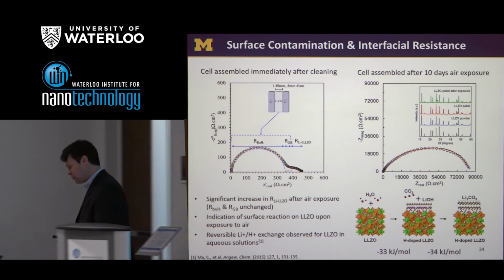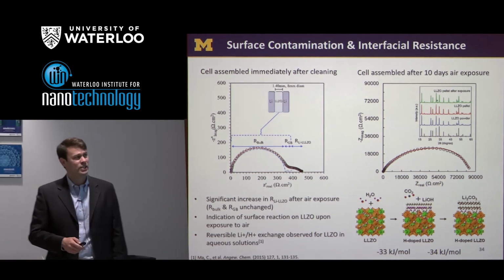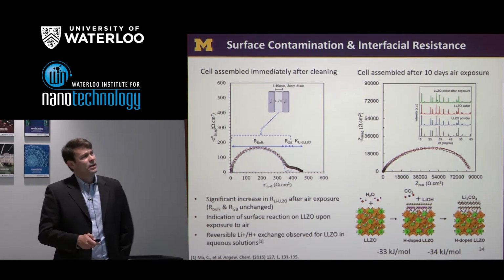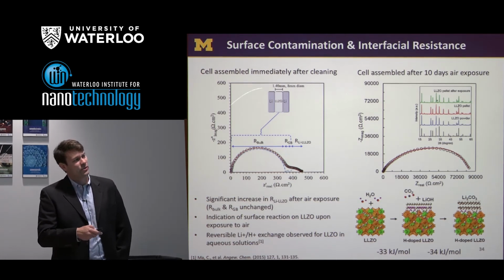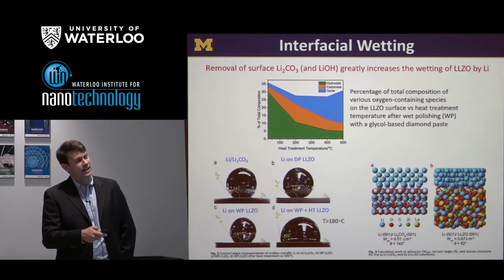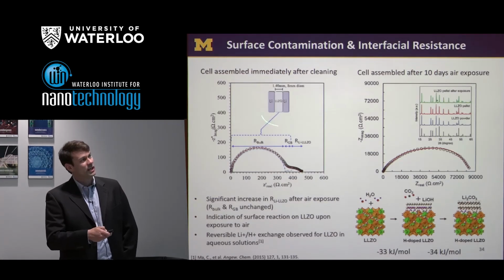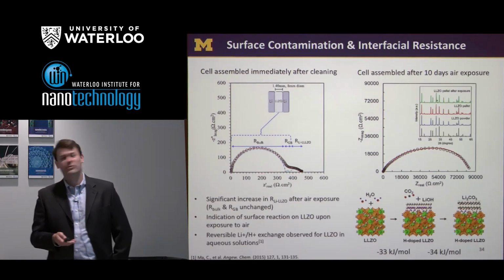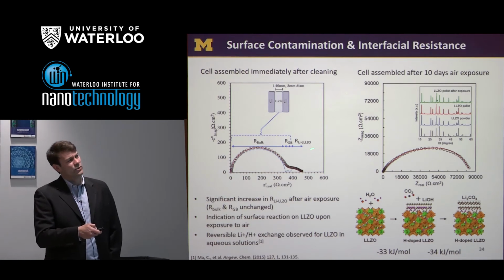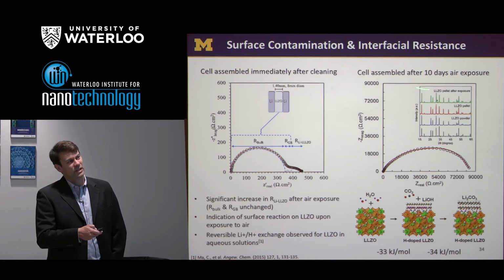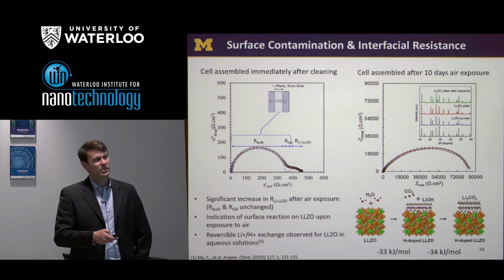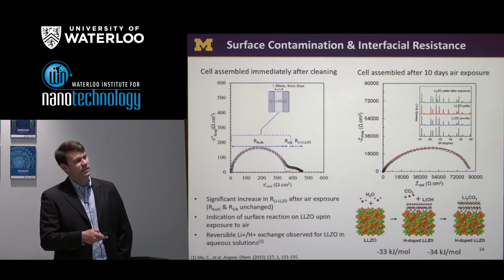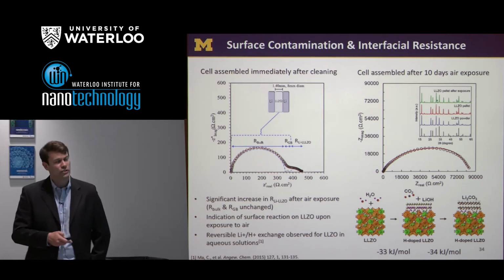So the reason this could be a problem is because of some surface reactivity associated with LLZO. So, here's an example of some Nyquist plots for, again, that symmetric cell assembled without the LLZO coming into significant contact with air. In that case, looking at the tail here to the right, the component of the resistance due to this interface is rather small. But if you let this LLZO system sit for 10 days under air, in fact, you can't even see these other 2 resistances. Basically, this interfacial resistance blows up and is huge.